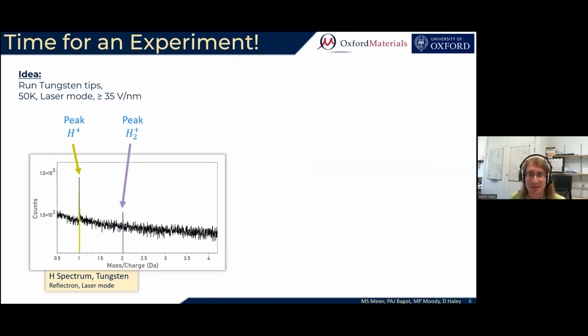So we have just learned that there's possibly something interesting happening with hydrogen in laser mode experiments at high electric fields. So what we do is we do a couple of experiments just to confirm and to see what might be going on there. We run tungsten tips because tungsten is naturally a high field material, so we can easily get APT runs at high electric fields out of these. And what you see here is the contaminant hydrogen spectrum in a tungsten tip that was run in laser mode on a reflectron machine. And indeed, both of the hydrogen peaks are here. So far, this is in agreement with our observations on archive data.